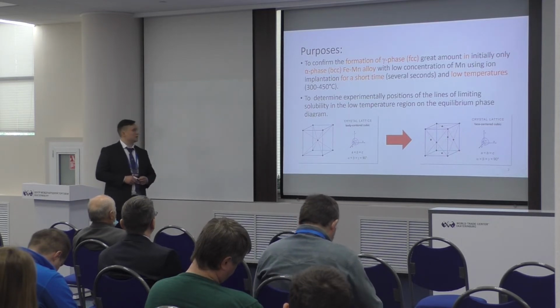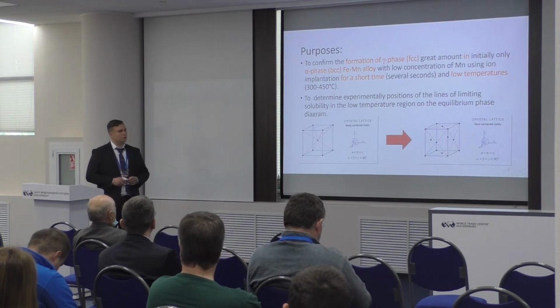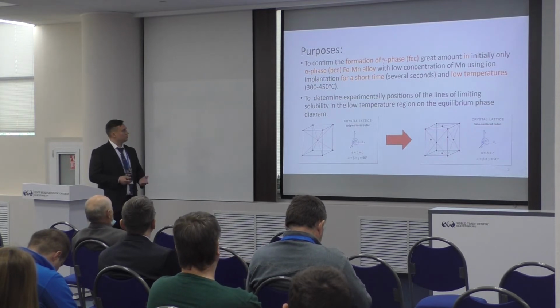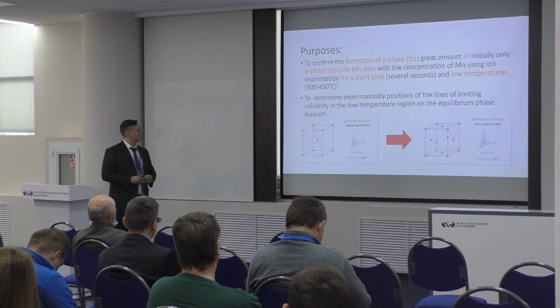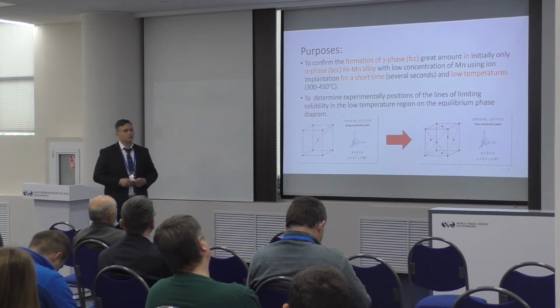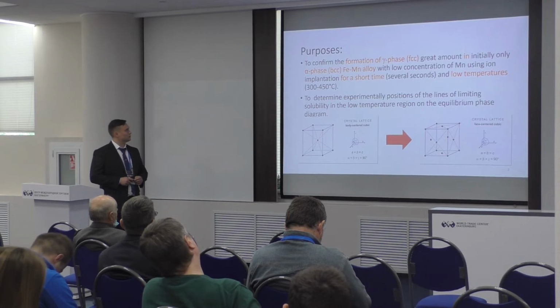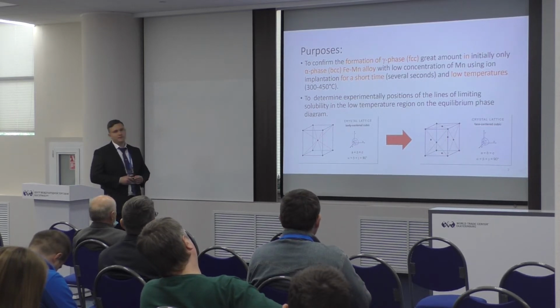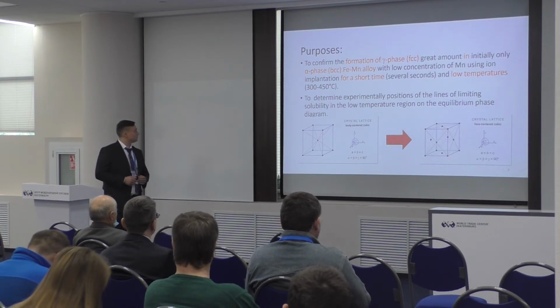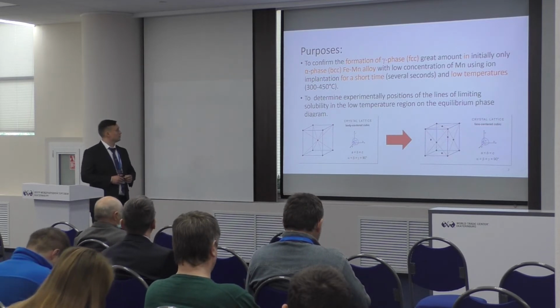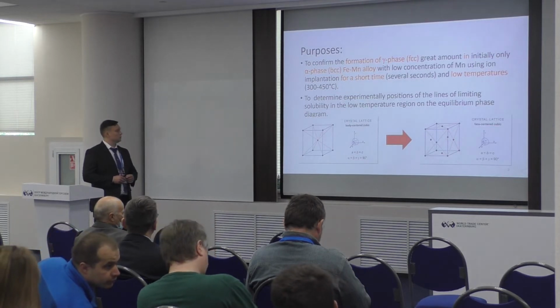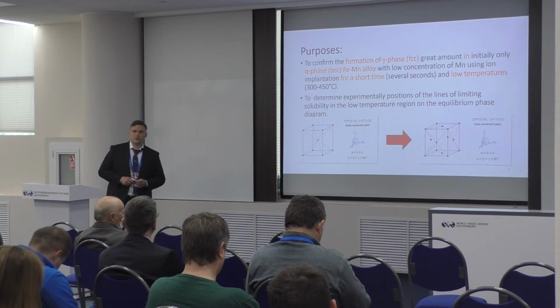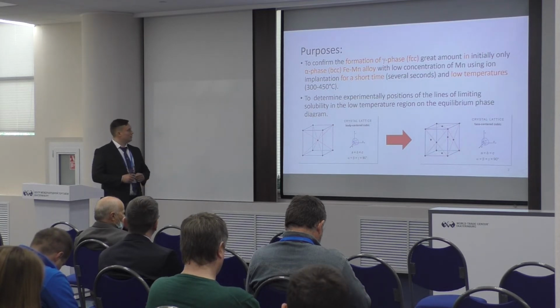There is some research about this method, but not using thermal processes or ion irradiation. They use megaplastic deformation. Also my purpose was to construct the low temperature area of the equilibrium phase diagram of the system iron-manganese.